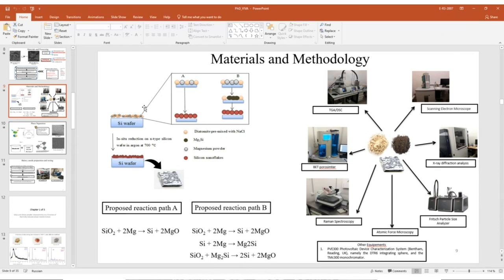Okay. Thank you very much, Prof, for your question. So we actually explored this for other substrates, and we realized that it was not feasible. And the reason it's not feasible can be seen from the reaction path proposed in B. The intermediate magnesium silicide phase formation is critical for improving the nanostructured silicon coating on top of the substrate. And so without the formation of this phase, you produce silicon powder on top of any other substrate, but you are unable to get the produced silicon bonding directly to the substrate. Thank you very much.